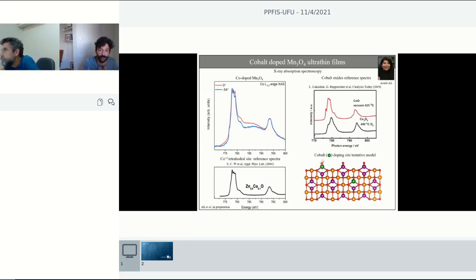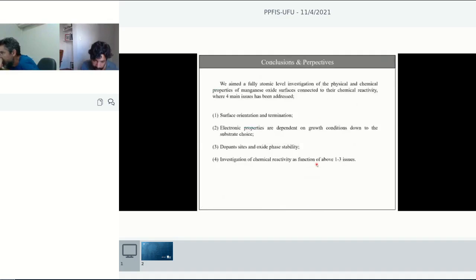And also we expect that some of this cobalt is actually sitting, of course, in the center of the film, but most of it in these low coordinated sites on the surface, something that would promote the chemical reactivity related with the doping of the film.